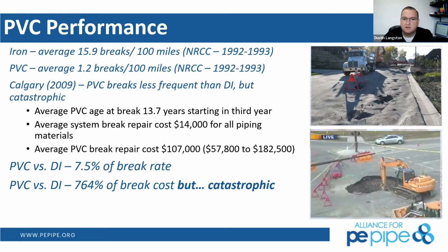But in that time, they started to realize that, hey, even though we're having 7.5% the break rate of ductile iron, PVC, when it did fail, it was failing catastrophically in these axial long running cracks that would destroy whatever infrastructure was above it. And so even though it was 7.5% the break rate, it was 764% the break cost. So to excavate down to a ductile iron pipe and put a band clamp over a corroded area, very inexpensive, did very little damage above it. When a PVC pipeline came open, unzipped, if you will, it created a big pothole, a lot of damage.